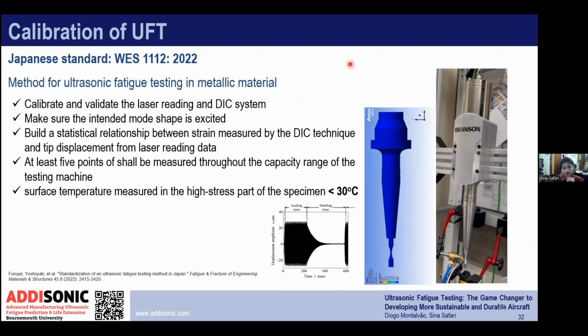In the third step, we can build a statistical relationship between the strain measured. What I mean by strain: we have this neck in the middle of the specimen, where we measure the strain using the DIC system. And then using the laser, we measure the tip displacement. Because we are assuming the specimen is in the linear regime, there is a linear relationship between the tip displacement and the strain in the middle of the specimen. So that's one of the steps that we need to carry out to find the relationship between the laser reading at the tip of the specimen and the strain in the middle section of the specimen.